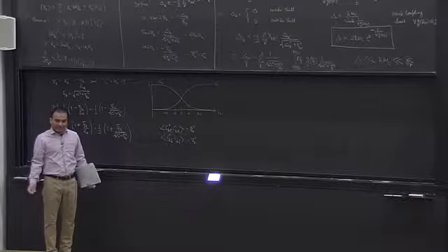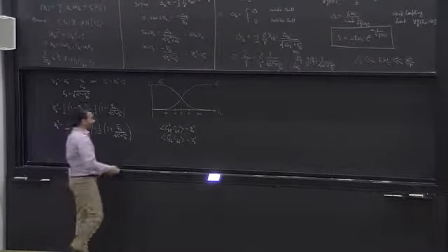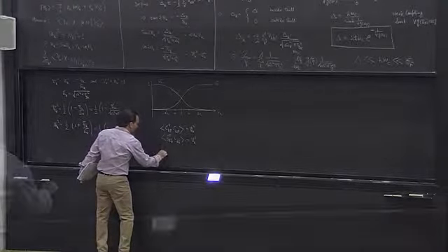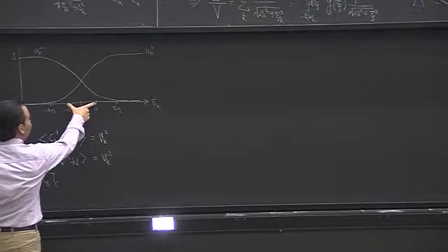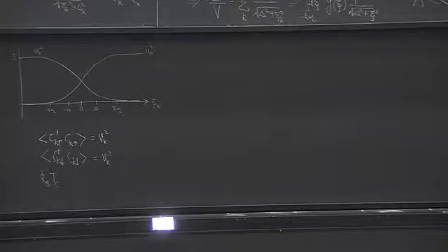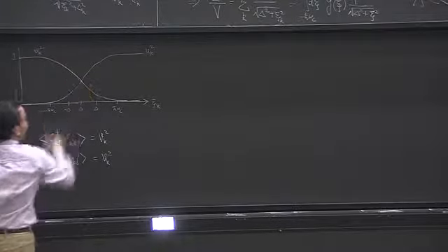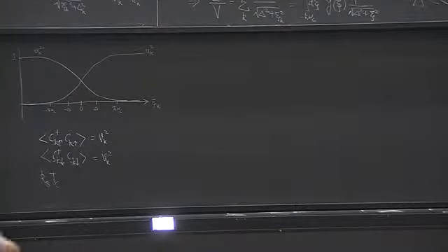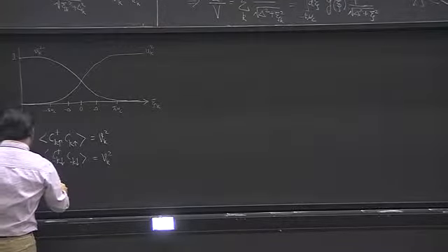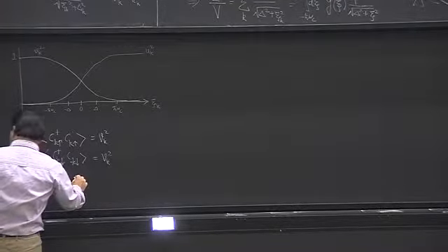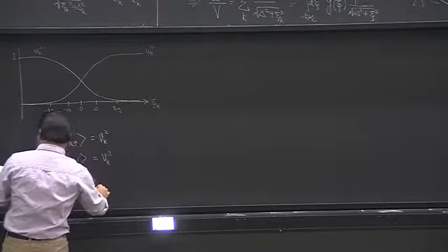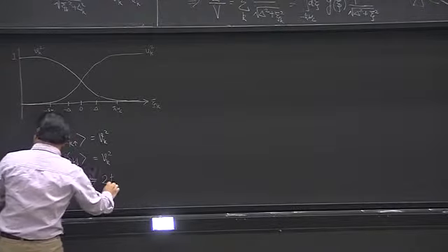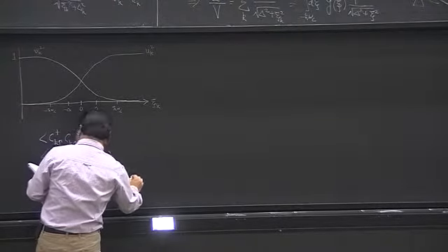This is an observation. From this observation, one can say that kBTc should be of the same energy scale as this new energy scale delta, because in a Fermi function you have this variation at the energy scale kBTc. So if you assume kBTc is of the same order as delta, which we have calculated within the weak coupling limit as 2 h bar omega c.